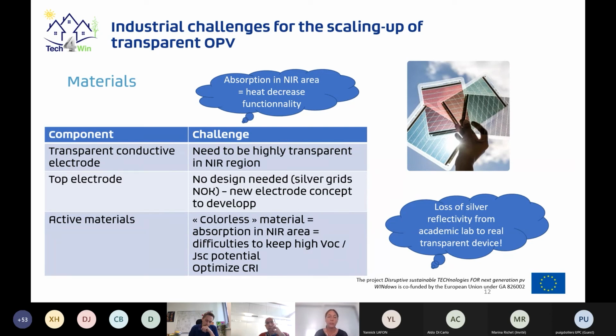One big interest if we develop this kind of material is that with materials absorbing in the near-infrared area, we have an additional functionality, which is heat reduction, combined with the photovoltaic effect, so of big interest for buildings, mostly in really hot areas. And one drawback for the transparent developments: most of the reference performances for OPV are evaluated at first stage with an evaporated top electrode, and we know that we lose a lot of JSC when we switch to a fully transparent top electrode because of the loss of the silver reflectivity. And then it's important to have some light management strategies, like we saw in the previous talks as well.